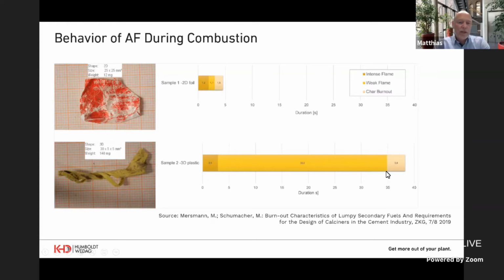So why is this so important? It is important because in the cement industry, and especially in the calciner, we have combustion in suspension flow. And premature dropout into material will cause problems in clinker quality and also in energy release. So what we learn from this is alternative fuel needs more attention, it needs more retention time, and it needs an optimized reactor in order to burn out.